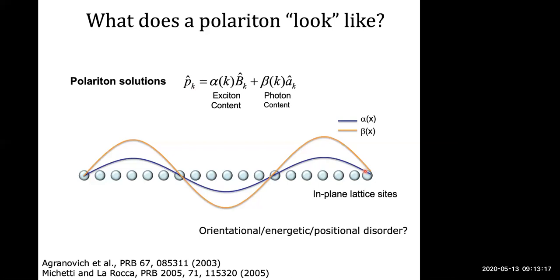Now, in most of these organic systems, we have quite a bit of orientational, energetic, and positional disorder. So what this tends to do is to localize the excitonic component of this polaritonic mode in space. And this was first discussed by Agranovich, and then nicely demonstrated in numerical simulations in this work by Michetti and La Rocca in 2005. And what they found is that in regions of the dispersion relation where the dispersion relations are relatively flat, so non-dispersive, states in these regions tend to be quite localized.